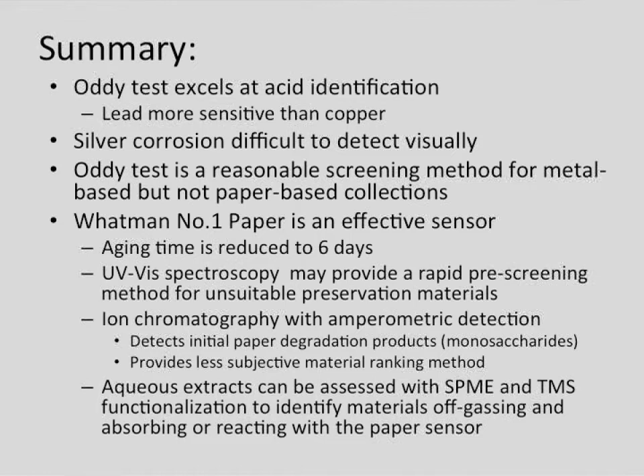The Oddy test is a reasonable screening method for metals, but you have to be super consistent about the way you run it if you want reasonable and useful results. But it's probably not ideal for paper-based or organic-based collections. We've proposed using this Whatman paper at the library as a sensor. The time for testing is 6 days rather than 28, so that helps. But the way we assess it takes a lot longer.